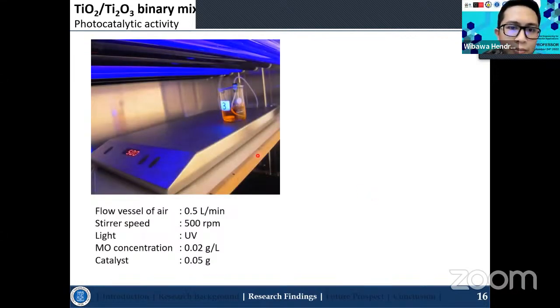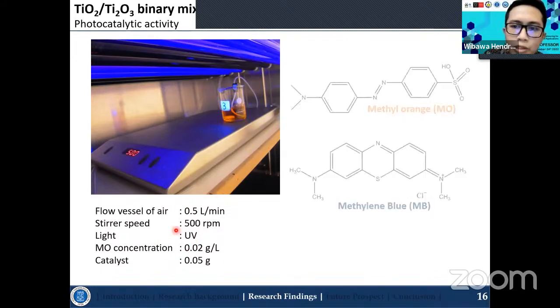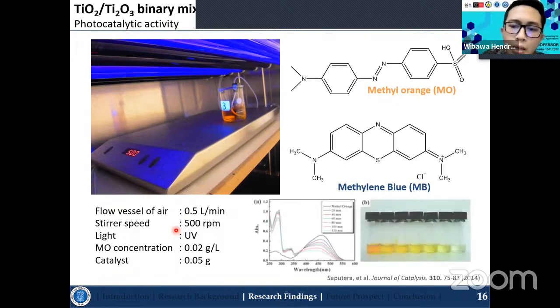I used very simple apparatus here, just a 100 ml beaker glass, and I used UV light. This is the UV light with a power of just 18 watts. We have around 5 UV lights in this case, and I purge with oxygen during the photocatalytic activity measurements. This is the operating condition that I use, with methyl orange as a model compound and also methylene blue. It can be seen here that the methyl orange is degraded as a function of time.